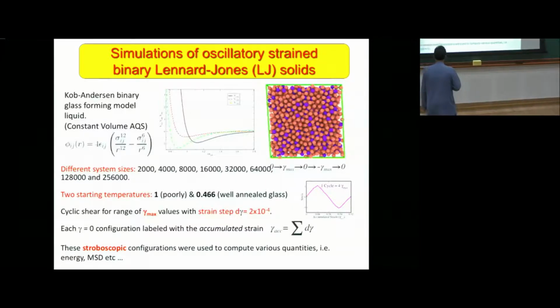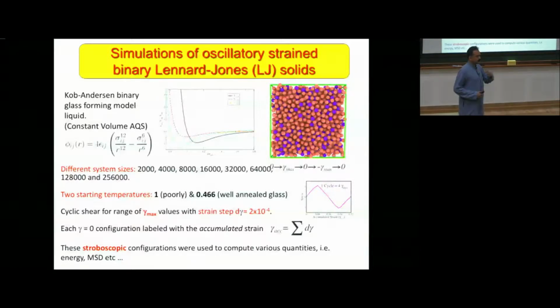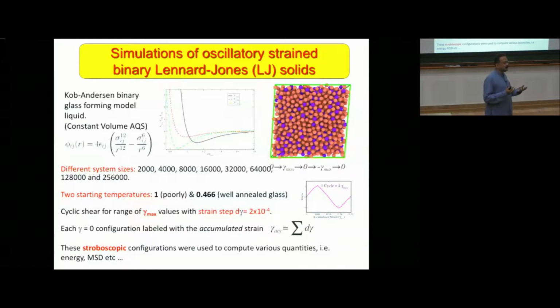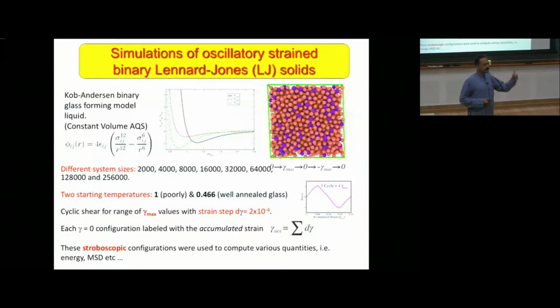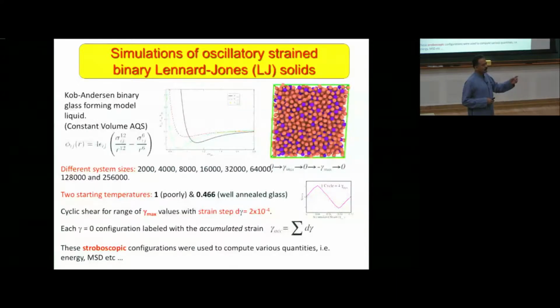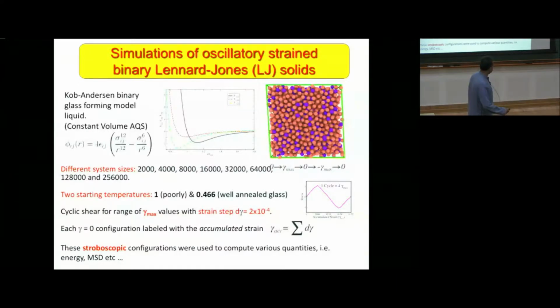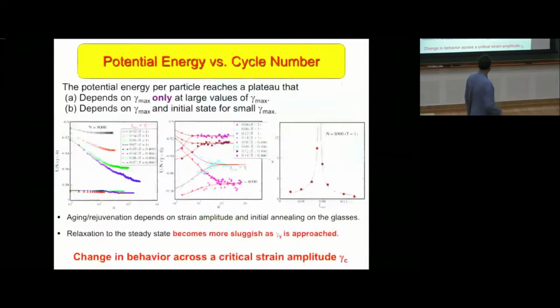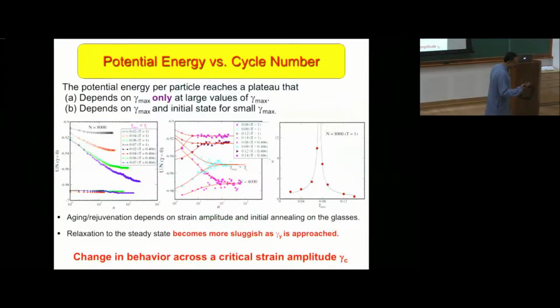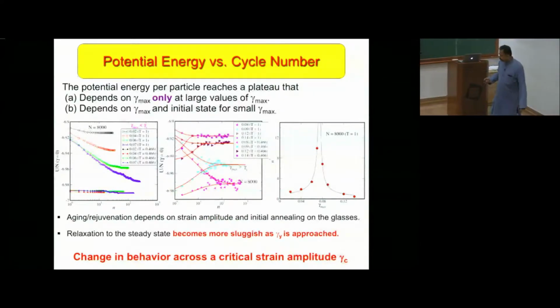Okay, so we're typically looking at stroboscopic configurations at the end of each cycle and measuring properties. And we have as our time variable the total amount of strain that is imposed, which is 4 times the amplitude times the number of cycles, which we call the accumulated strain. So what happens as we do this over a range of strain amplitudes is illustrated here.